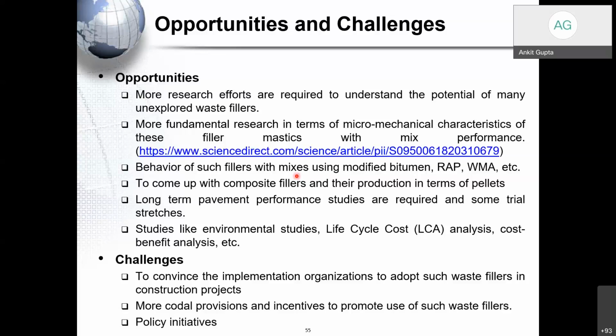These fillers have been used in normal mixes, but nowadays you will see that a lot of modified bitumens are coming. Warm mixes are there. Okay, the cold mixes are there. The RAP mixes are there. Okay, so with the use of these new kinds of mixes, probably the use of these fillers can again be explored. Again, the composite fillers, which I told you about, the glass powder as a filler. So the glass powder is failing for moisture. That does not mean that we can never use the glass powder, because it is showing some good properties in the rest of the other things. Okay. So the only thing is we can make composite fillers, meaning using the glass powder and adding some more calcium-based fillers or lime-based fillers, making it a composite filler.